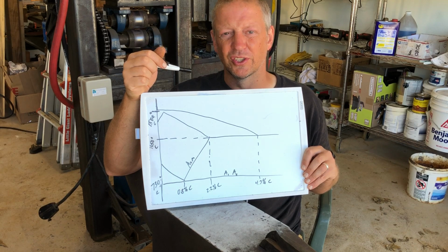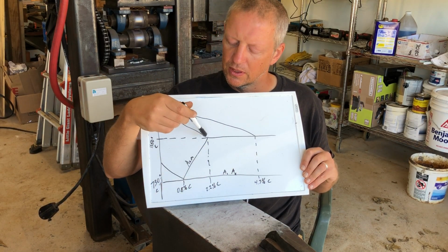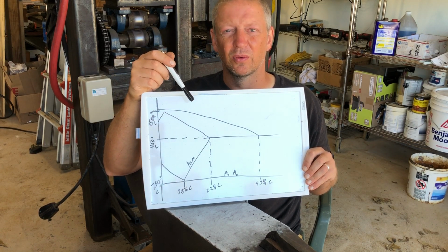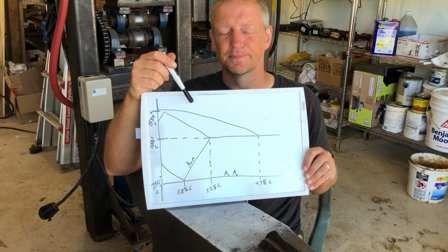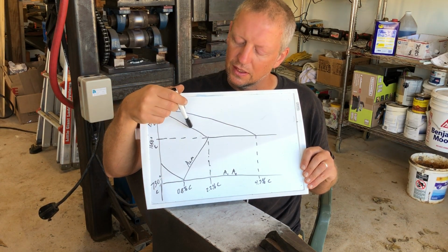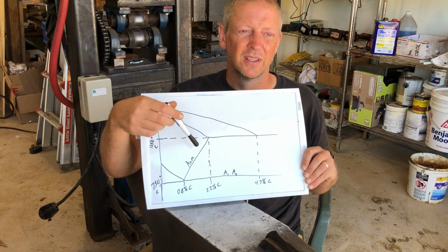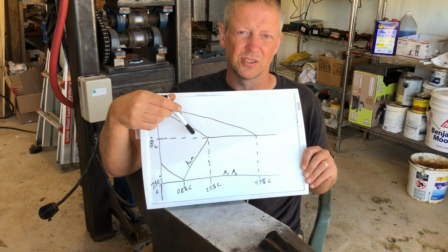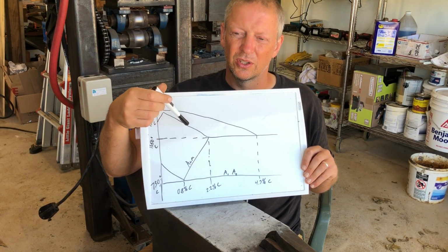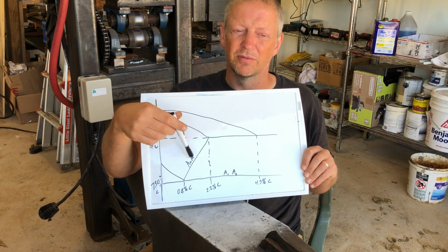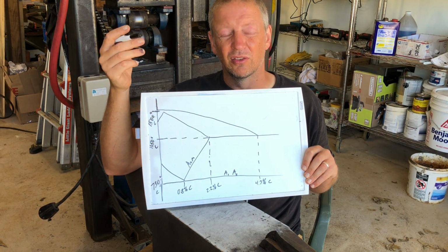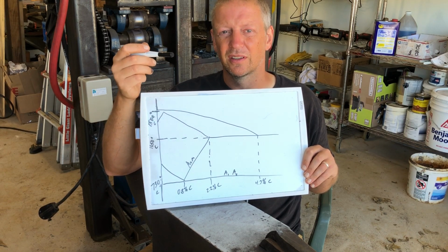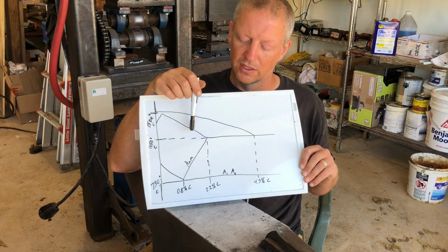Wootz is not homogeneous. So where that line is actually depends an awful lot on what your structures are. If you have heated and you have a lot of carbide, and that carbide has just dissolved, and now you are preparing to forge, that carbide dissolved or partially dissolved, and you now have a concentration of carbon around the carbide.